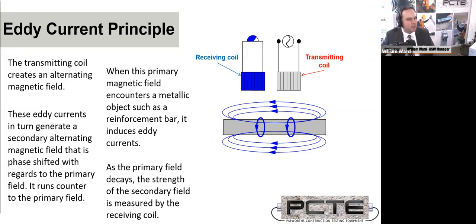Now we have Julianne Latham asking, if the bar diameter is unknown, how significantly can this affect the accuracy of the depth measurement if it's incorrectly set? Now, I don't have slides in this presentation that go into deep analysis of precision, but a couple of key things to keep in mind is that it is more affected close to the surface. So if you've got a very thin cover, 10, 20, 30 mils, a slight variation in reinforcing bar is going to make a big difference. The effect of being a little bit wrong in your bar diameter is reduced the deeper the overall cover.